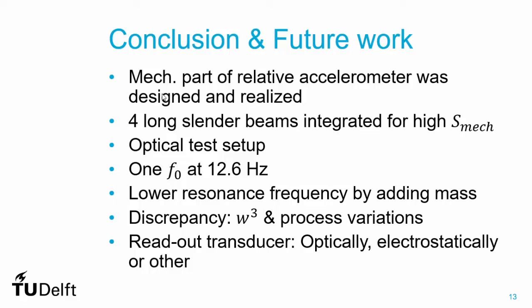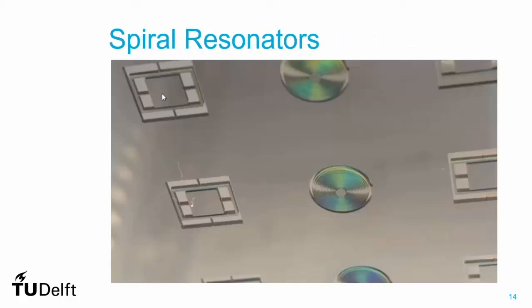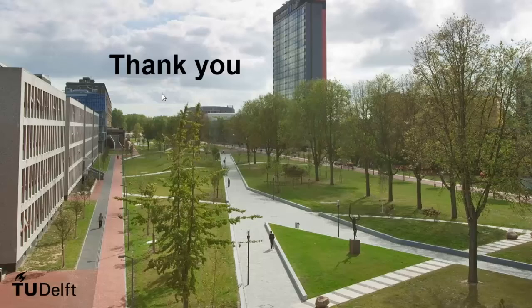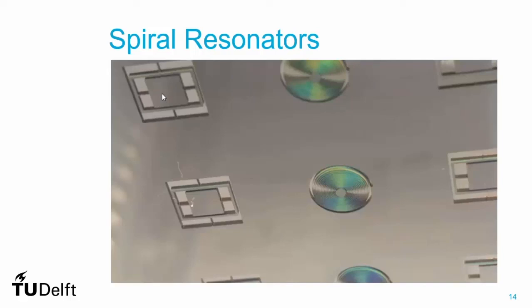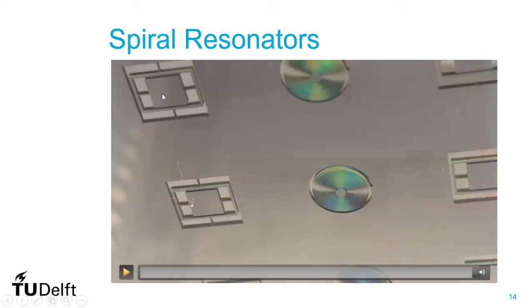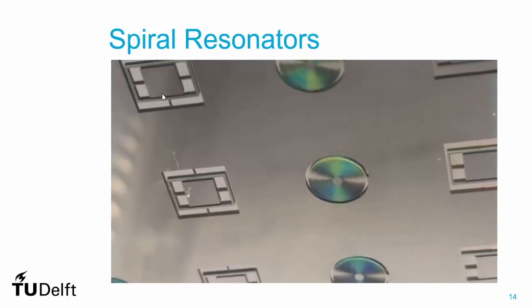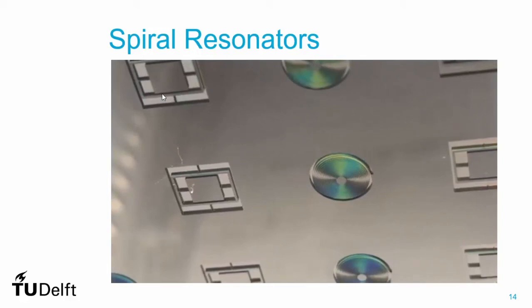A video shows a different structure — a spiral resonator and other resonating structures which can be etched through a wafer and measured optically in the clean room to assess process variation. The spiral functions as a spring with a center mass, and by focusing a microscope on the center mass displacement we can evaluate beam width variation during etching. This elaborates on the process dependency of the design.